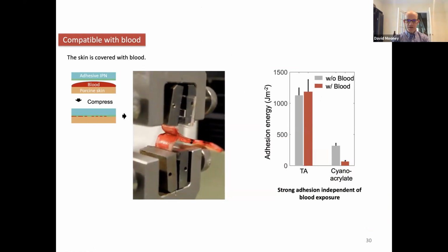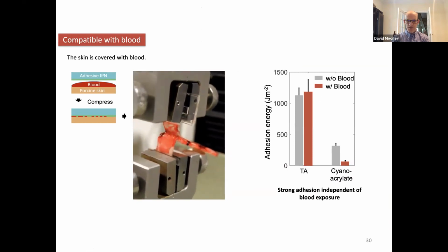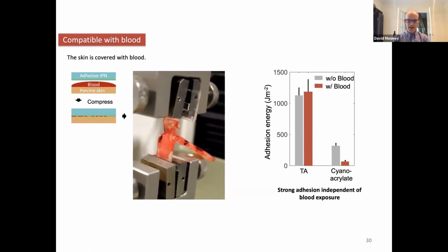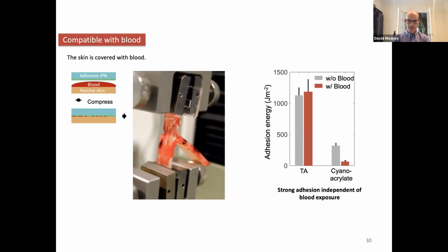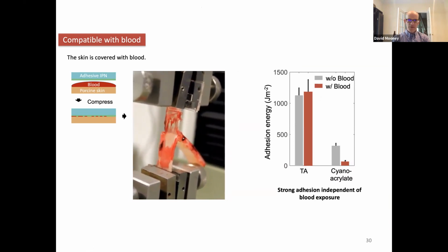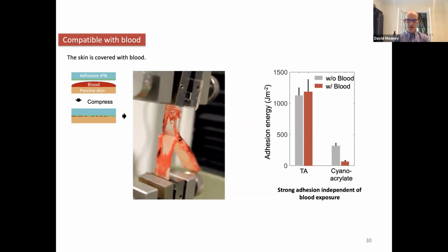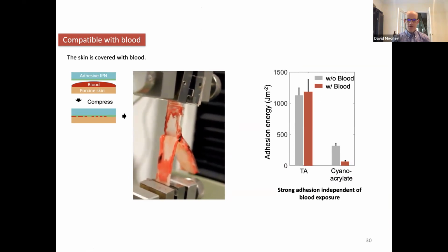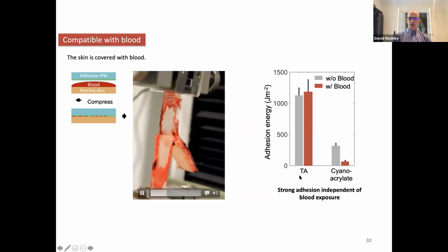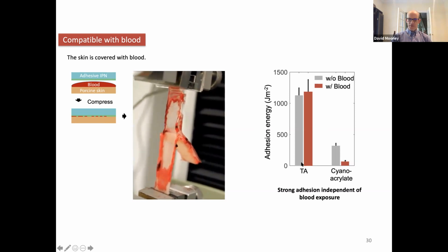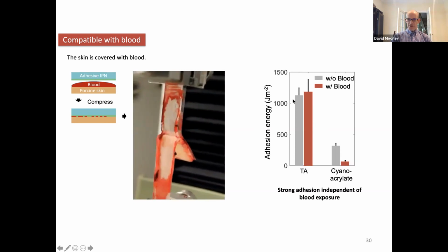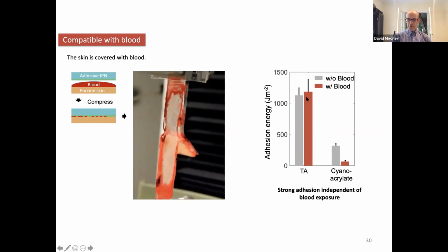This is just a peel test of one of these gels that's been placed onto porcine skin. In this case, he actually coated the porcine skin with blood before the adhesion to determine whether or not the presence of blood would inhibit the ability to form strong adhesion. And what you can appreciate is he's forming this TA, the tough adhesion. He's getting adhesion energies in the range of 1,000 joules per meter squared.